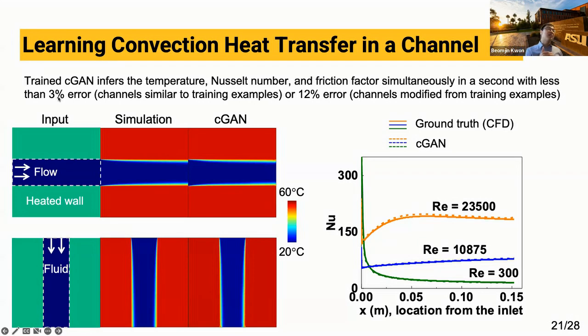So the trained generator was able to infer the temperature, Nusselt number, and friction factor distribution simultaneously within seconds with less than 3% error, especially for the channels having similar geometry to training examples. And the error increased to 12% for the channels having modified geometry.